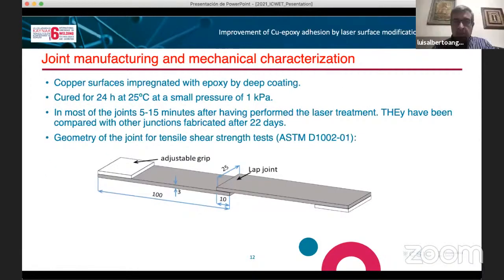So in order to fabricate the joints, the copper surface after cleaning was impregnated with epoxy by dip coating. Then they were cured for 24 hours at 25 degrees, applying a small pressure of 1 kilopascal. In most of the cases, the joint has been fabricated just 5 to 15 minutes after having performed the laser treatment on the copper surface. But in some cases, we have also checked what happened as a function of time, and the junctions have been fabricated 22 days after the laser treatment.